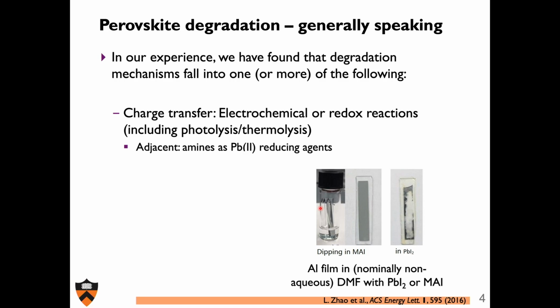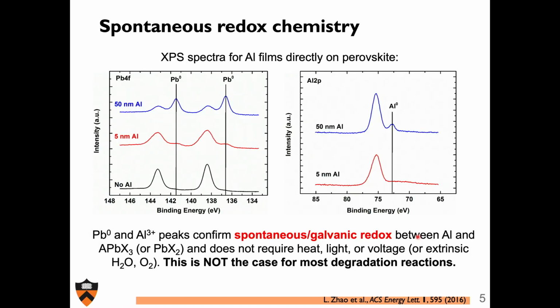And here's a really simple experiment that can be done in any lab. If I take a film of aluminum on a little piece of glass and I dip it in methyl ammonium iodide, nothing happens. But if I dip it in lead iodide, it gets completely corroded and it goes away in seconds. And what's behind that is an electrochemical reaction. And this is a really spontaneous one. This is an obvious one. This is the one that we first published 6-7 years ago now. Sorry, more like 8 years ago now.